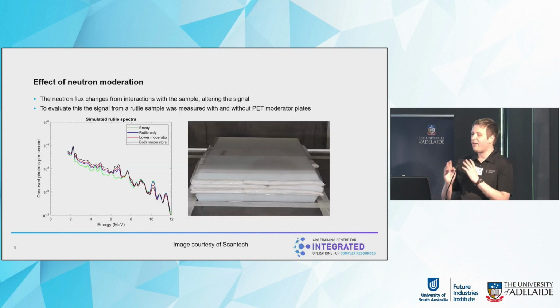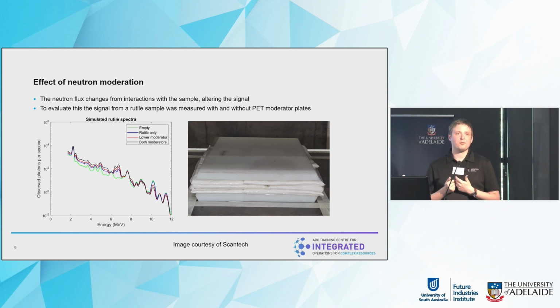So, we mentioned the impact of neutron moderation, which is beneficial for measuring larger samples. However, if you want to measure a small amount of material, it's possible to use a moderating material to reduce the neutron energies and get a boost in the sample activation. To test this, a consistent 15 kilogram titanium oxide or rutile sample was measured, both alone, with a moderating polyethylene plate below, and sandwiched between two moderator plates, as shown on the right.